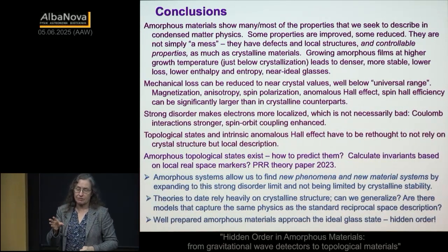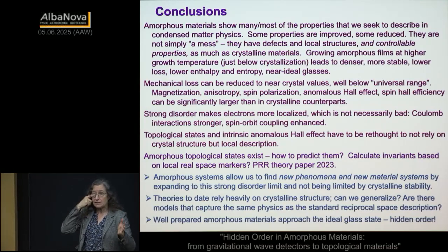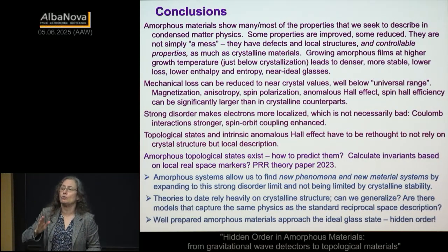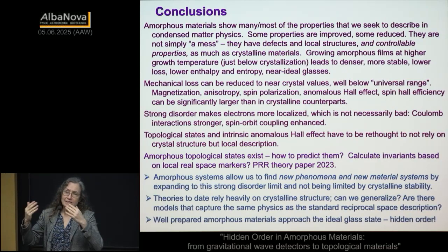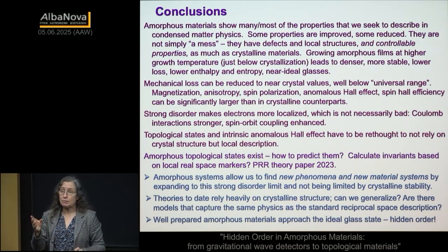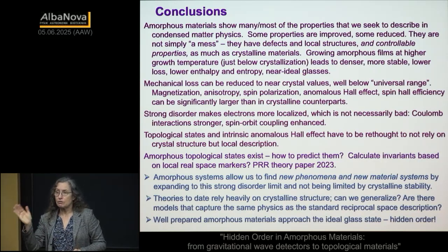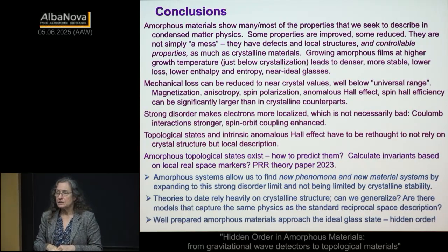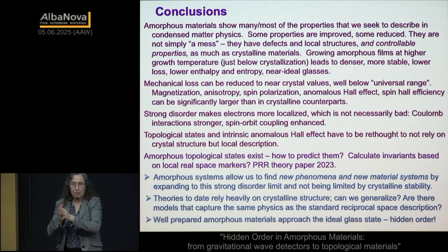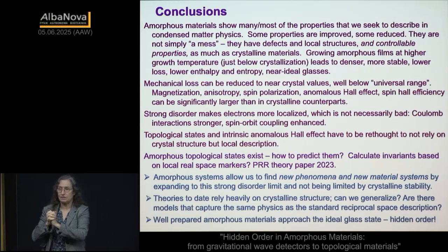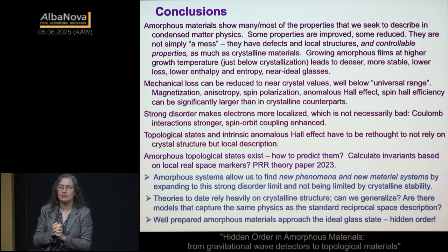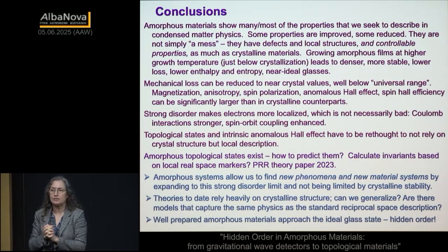So the diffusion limited aggregation that you're talking about, we definitely see. In fact, if you start growing at very low temperatures, you do see much more of that dendritic process, and that is what happens when you don't have a lot of mobility. But start raising the growth temperature, even in those early papers, if you start looking at the effect of raising the growth temperature, that surface diffusion wipes out the diffusion limited aggregation. But there is yet another competing process which I feel like I should mention, even though you didn't raise it. At some point you start crystallizing. So if you give it a lot of mobility, you'll actually nucleate, crystallize. And the important word there is nucleate.